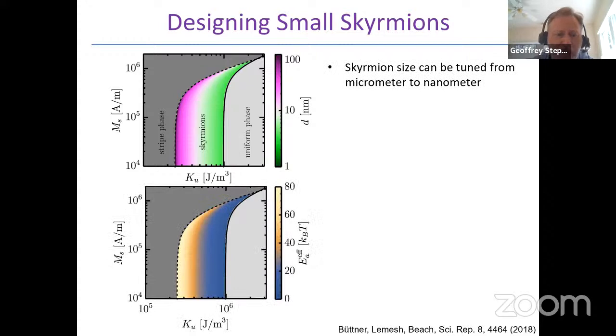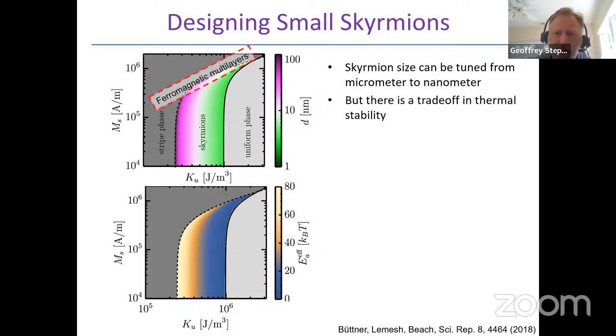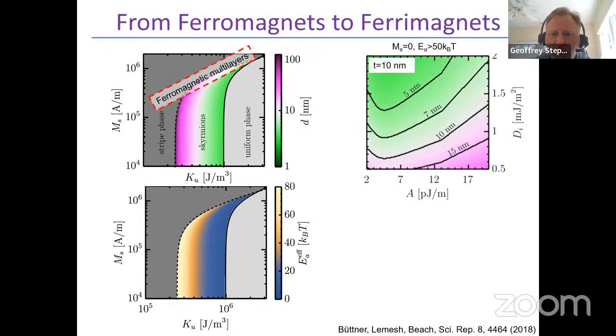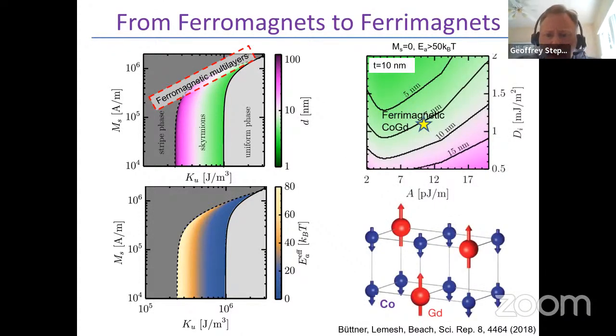And so Felix Buettner, when he was in my group, developed an analytical theory that has several ansatzes for the various energy terms for magnetic skyrmions that allows for a very rapid computation of the materials parameter space to try to understand both the energy barrier for annihilation of a skyrmion, so the stability, and also the size of a magnetic skyrmion. And what was found was that there's really a trade-off between size and stability, at least for ferromagnetic skyrmions. But for ferrimagnetic skyrmions, or materials with lower stray fields, and let me step to the key point here, one of the target materials that we looked at was cobalt gadolinium.